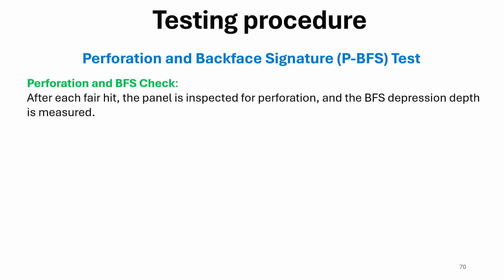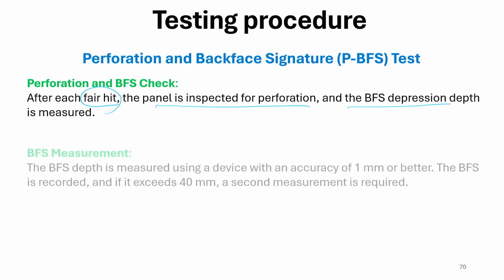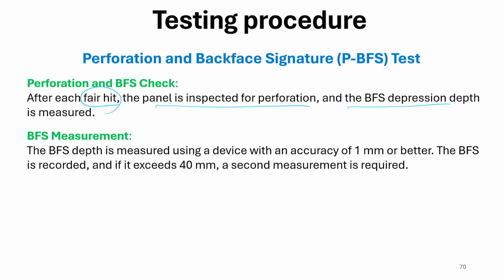Then perforation and back face signature checking will be there. After each fair hit, this is important, the panel is inspected for perforation and the back face signature depression depth is measured. Now, BFS, back face signature, depth is measured using a device with an accuracy of 1 millimeter or better. The back face signature is recorded, and if it exceeds 40 millimeter, then a second measurement is required.